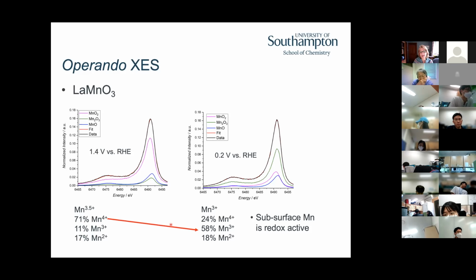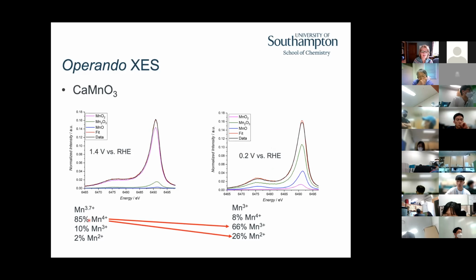And as we change the potential, we reduce the sample, the manganese 4 is going to manganese 3, the fraction of manganese 2 is not changing, right? So that tells us several things. My surface area is not great enough to account for all of this change, so the subsurface manganese must be redox active. But it's also telling me that I'm not accessing that manganese 2. I'm not wandering off from where I want to be. To maintain activity, I need to stay manganese 4, manganese 3. The calcium manganate, on the other hand, started off with an average oxidation state of 3.7, and it's easily over-reduced, right? So we wind up making much more of this manganese 2.